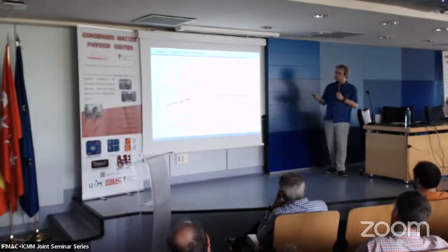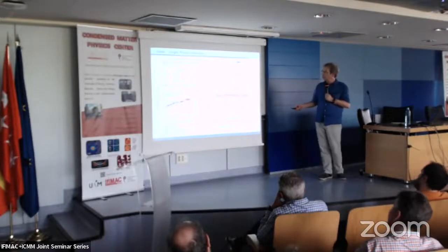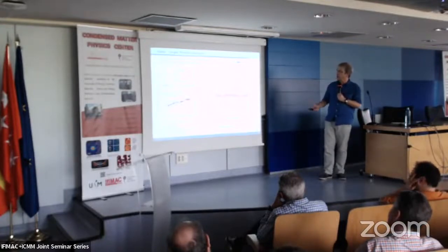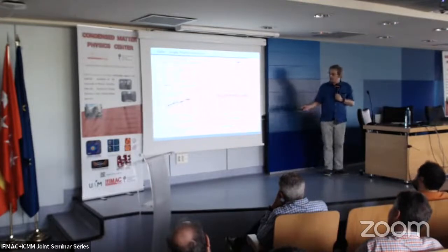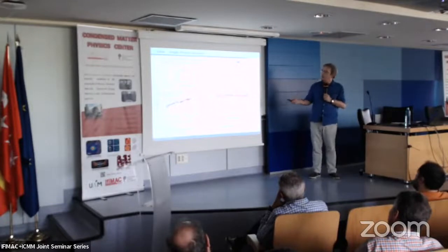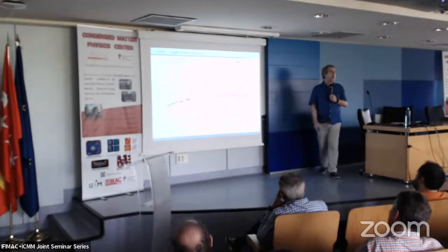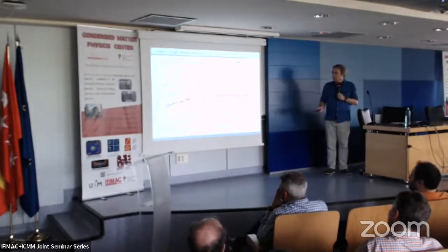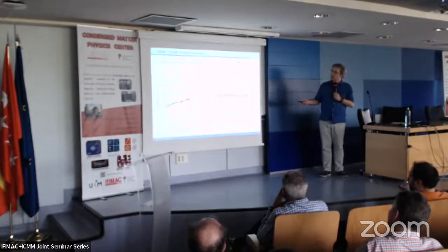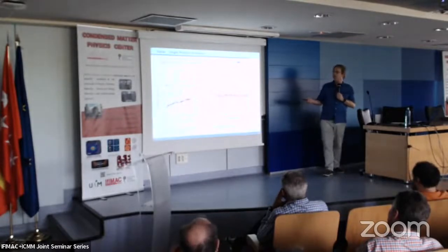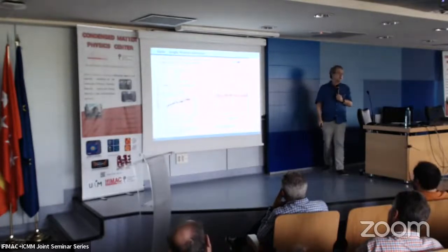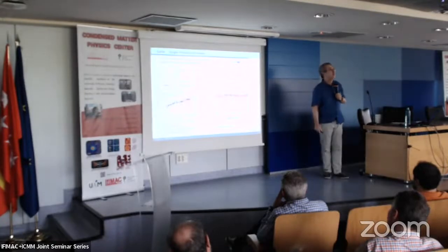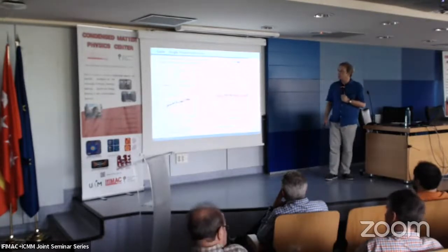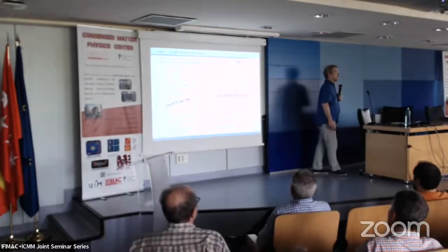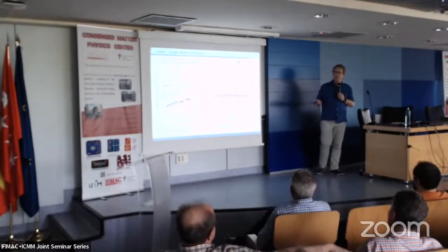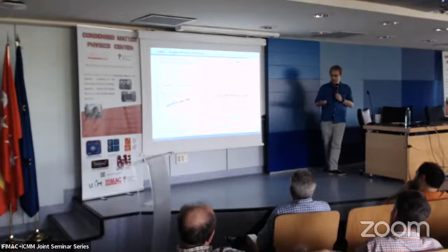The proof of the single photon emission is this black curve, which shows anti-bunching with a minimum at zero time delay, which we measured when detecting the exciton peak here in this correlation experiment. The big surprise was that making the same experiment, only detecting in the double exciton, the bi-exciton, we measured the opposite, a bunching. And until now, we don't have really an explanation for this bunching effect, which was not seen before.